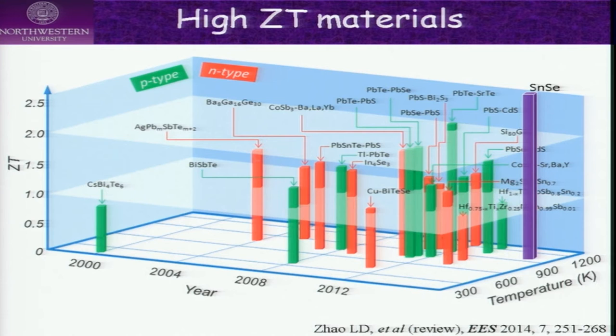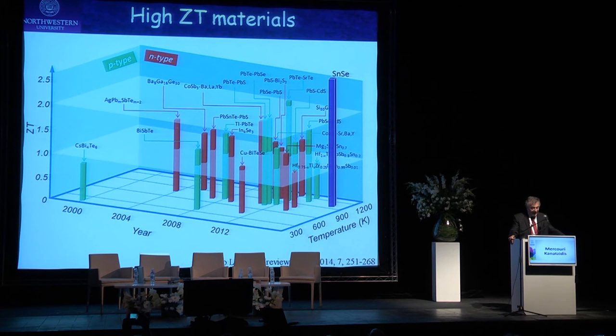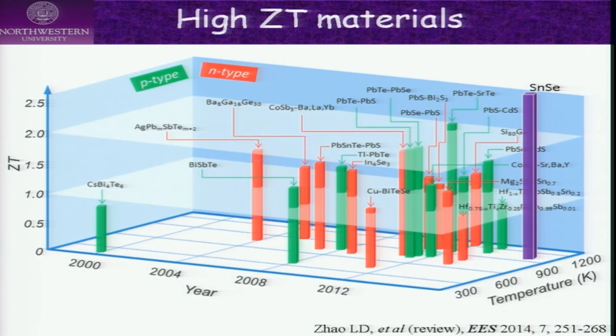We were able to beat this ceiling of 1 in 2004 with 1.4, 1.6. We generated a family of materials that did that. Then other groups generated their own breakthroughs with different materials. And later, we breached the ceiling of ZT of 2 with a few materials, with lead tellurium and strontium tellurium, for example.